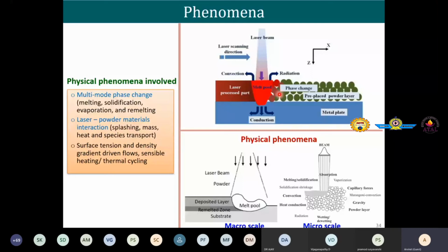And these happen at different scales. For example, what is shown here is at macro scale. At micro scale, it is even more complicated because we need to see the wetting behavior of powder particles with the melt pool, the interaction of the laser with the powder particles and then with the liquid, capillary forces, vaporization, laser absorption, laser transmission, laser reflection. Heat convection, heat conduction in the melt pool, Marangoni convection in the melt pool, shrinkage, melting and solidification phase change: all different kinds of phenomena at different scales.